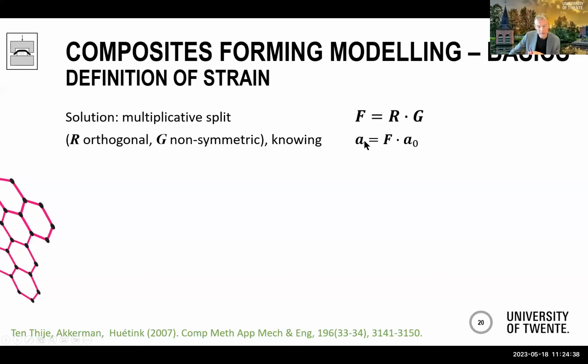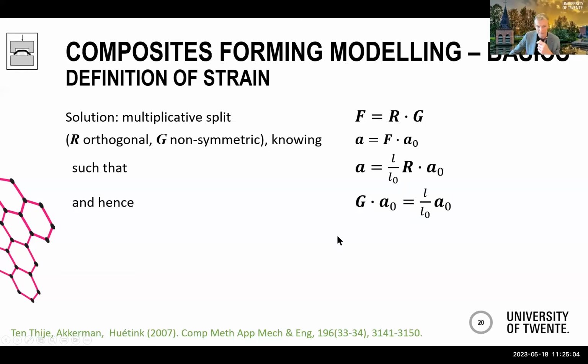We know that the current fiber direction depends on the initial fiber direction transformed by means of F, the deformation gradient. And what we wish is that the length change, any potential length change, is not part of R. And bringing that together, that means that G, our non-symmetric deformation tensor, times A naught is equal to this length change times A naught.